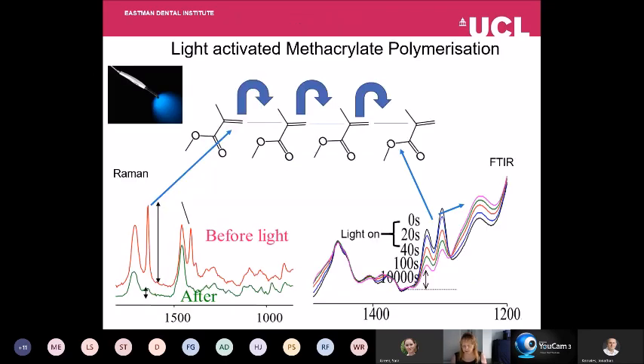When you expose the methacrylate to light, what happens is you start a chain reaction that joins all the methacrylate monomers together. What we found is we can use a Raman technique in order to look at how much monomer is remaining. What we find is that there is a peak that's due to vibration of this carbon-carbon double bond, that when the material polymerizes, that peak is lost. So the height of the peak after polymerization, divided by the height of the peak before, tells you how much monomer is left in the system.